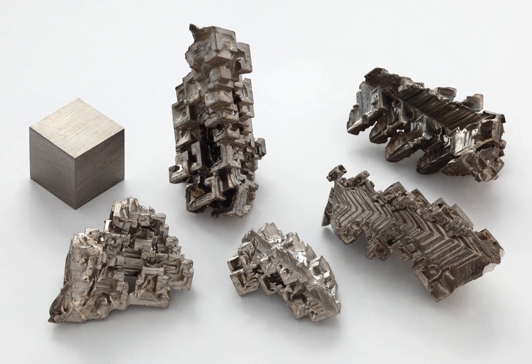Bismuth expands 3.32% on solidification, therefore, it was long a component of low-melting typesetting alloys, where it compensated for the contraction of the other alloying components to form almost isostatic bismuth-lead eutectic alloys.